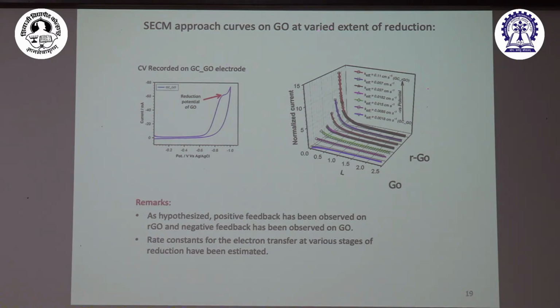Then what we did, we measured the SECM approach curves at various reduced states, applying minus 0.2 volt, minus 0.4 volt, minus 0.8 volt. And you can see here, initially the probe showed negative feedback, and once it's reduced more and more, it starts showing positive feedback. In fact, we measured the effective rate constant by using the approach curve in the in-between case, to determine the rate constant of charge transfer.